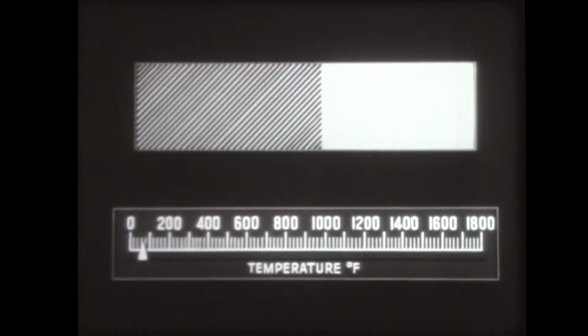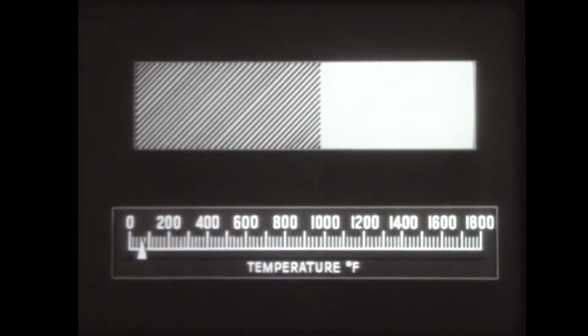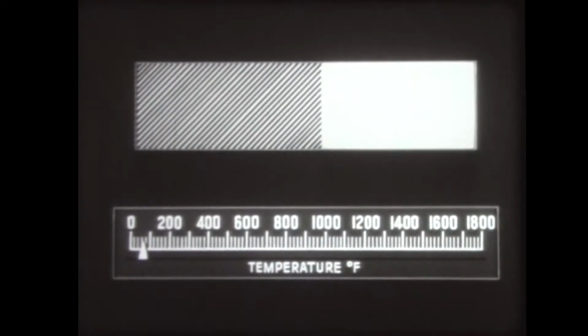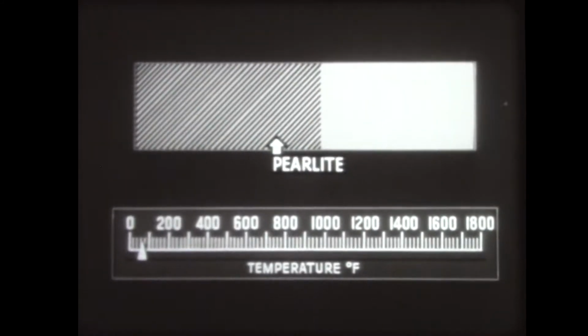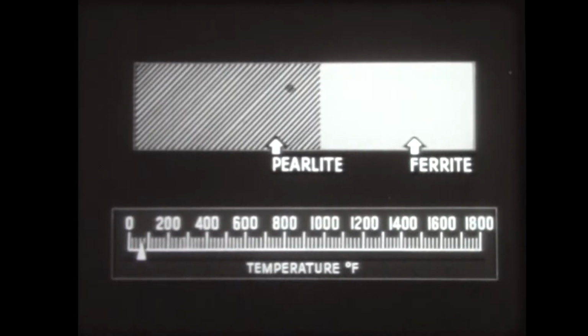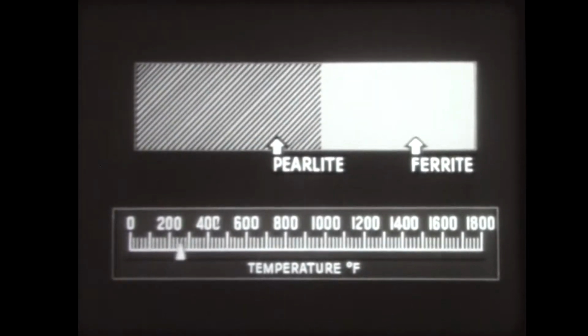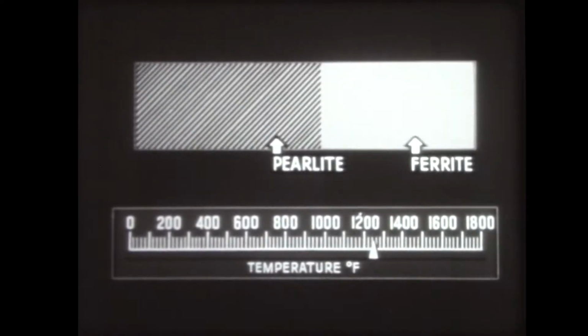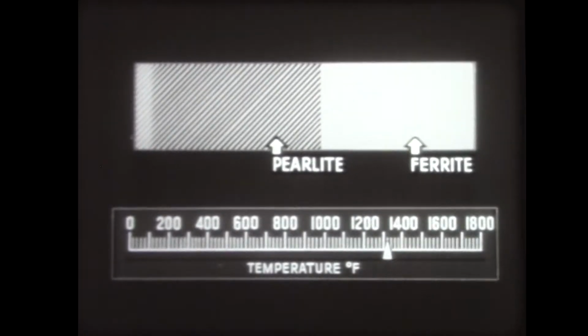Now small changes have taken place in the pearlite areas. In this micrograph, we can see that new areas, light gray in shade, have formed. What happened? Here is a graphic representation of the steel in its original condition. This represents its pearlite area, and this its ferrite area. When the steel attained a temperature of 1,320 degrees, some of the pearlite formed a new crystal structure, austenite.